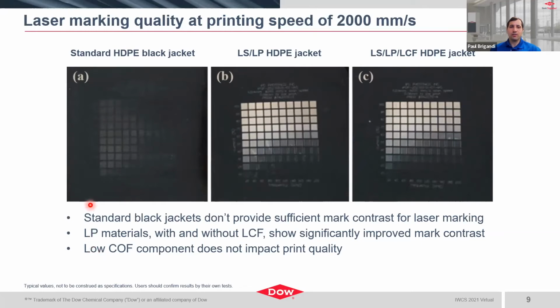So a couple key things that you'll see from this picture, right, is the first one is very low contrast when we consider the highly loaded carbon blacks, or the 2.5% loaded carbon black sample. So you don't get as good a print contrast there when you have the high loadings of carbon black. And thus these laser printable versions take advantage of being able to lower the carbon black loading such that you can print, but also maintain that print quality that you're looking for.